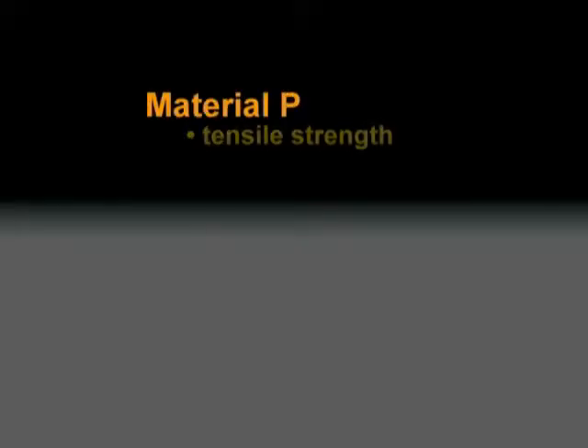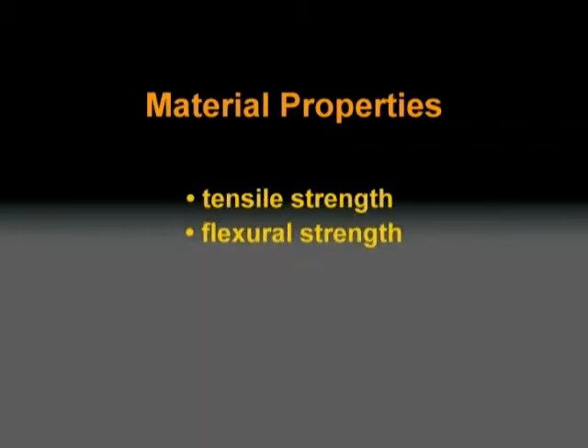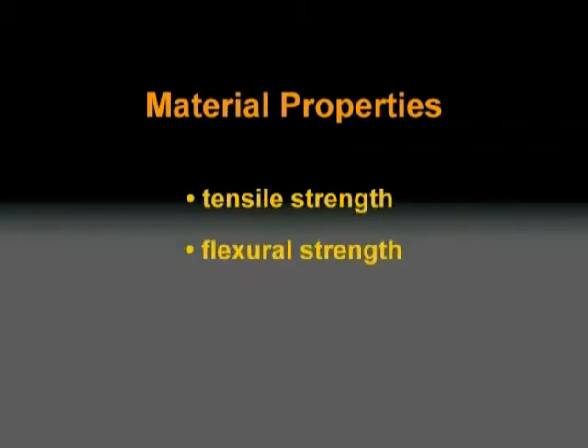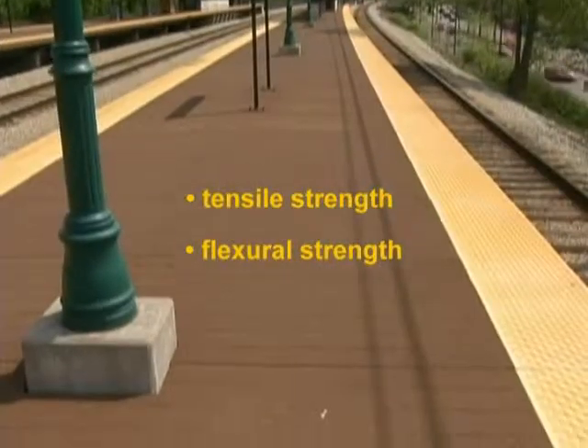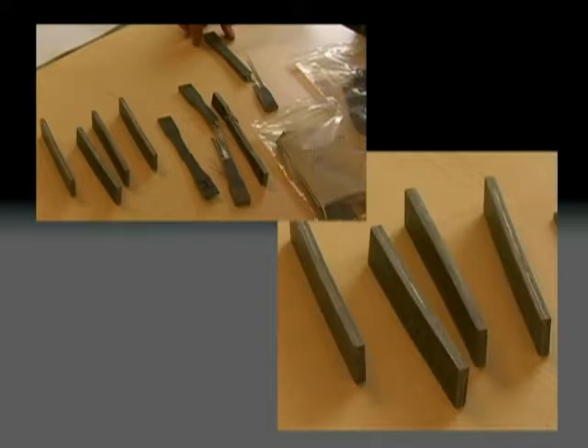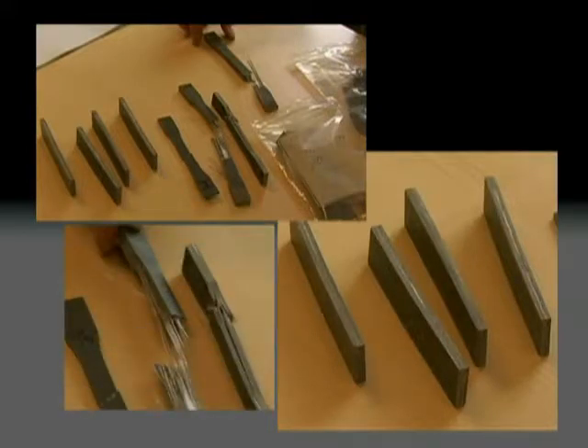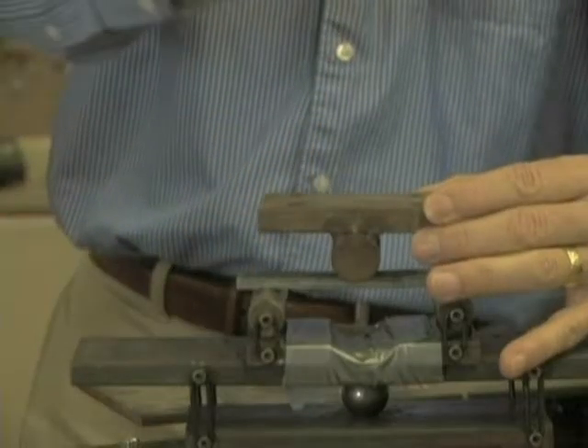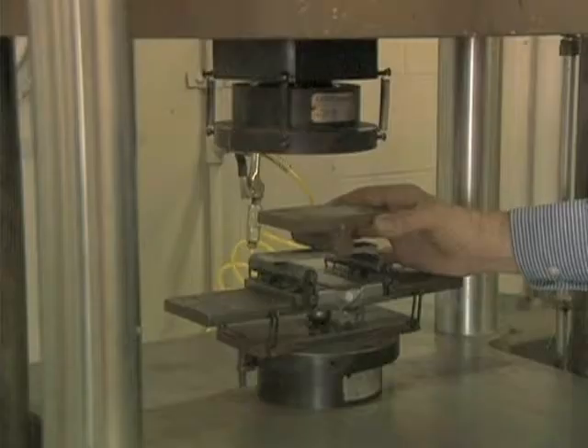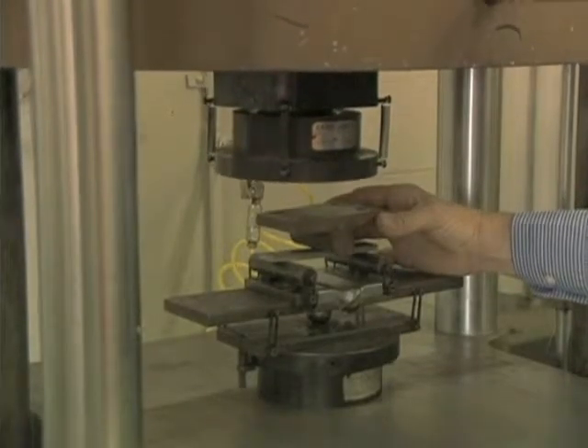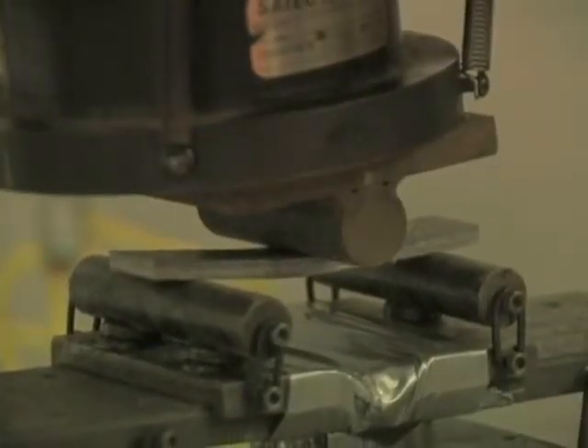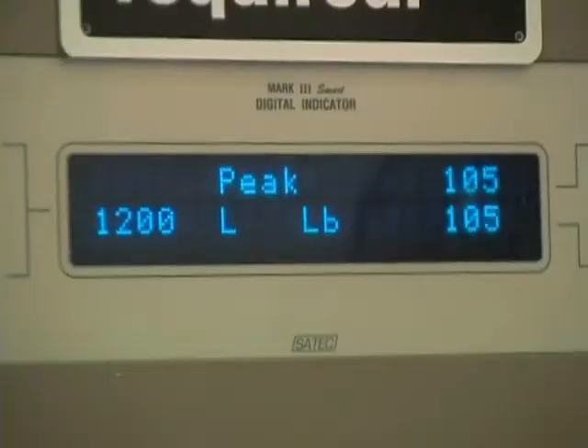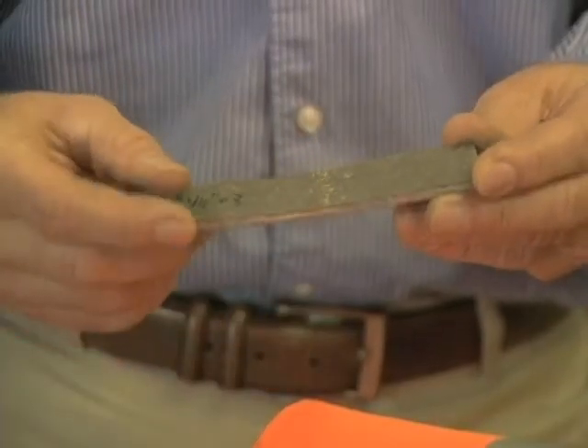And in order to do that, we had to get material properties. The two in particular that we needed for our calculations were the tensile strength and the flexural strength of the product, the strengths of those elements. So we had Engineered Plastics cut up a sample panel into test specimens to do flexural tests and tensile tests. The original testing was intended to show the load capacity of the Armor Deck panel. And the subsequent testing that we did was to support the calculations that we were doing to determine load capacity ratings, what the City of Chicago was asking for to satisfy that requirement of the city.